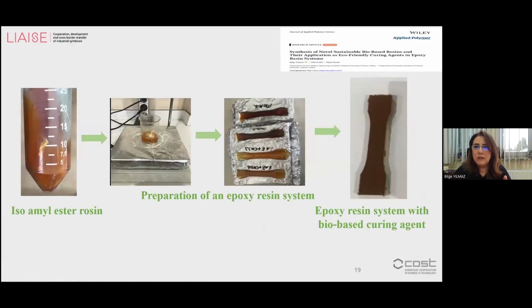And we also produce isoamyl ester rosin to use not only for the MDF, but also in the epoxy resin system as a curing agent, 2 different directions. And you see these experimental photos. We successfully produced epoxy resin systems, and also we published this research. Very many different areas you can adapt this polymer.